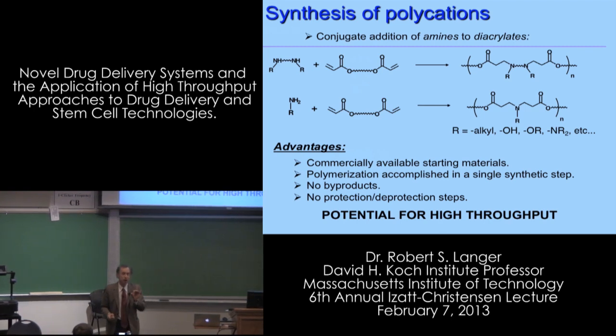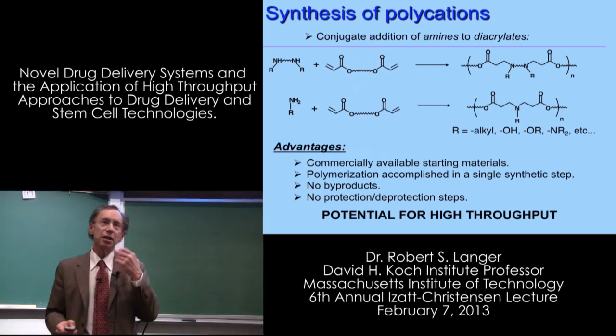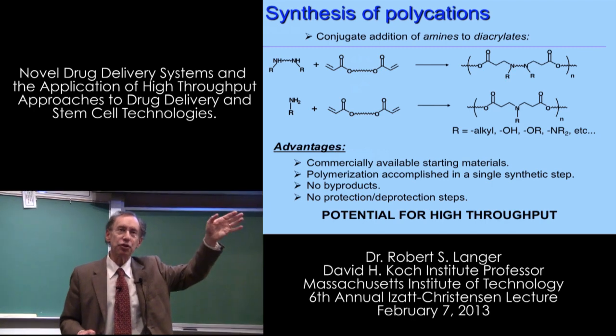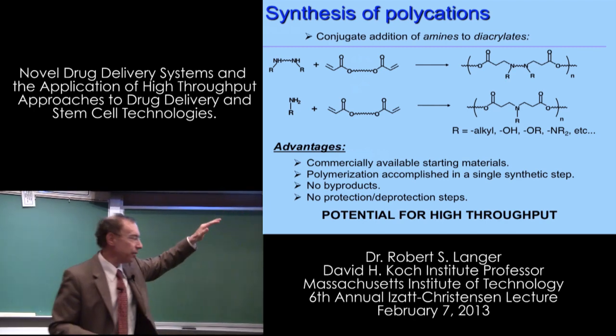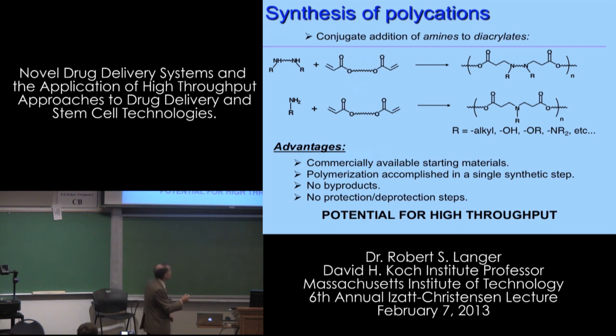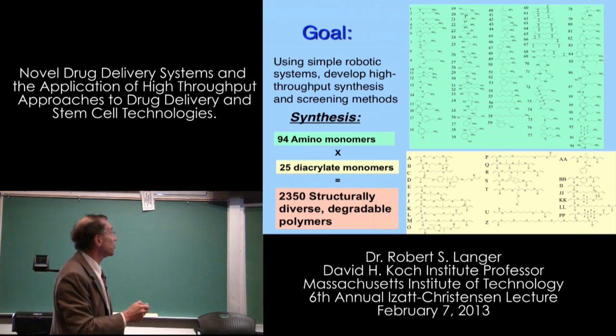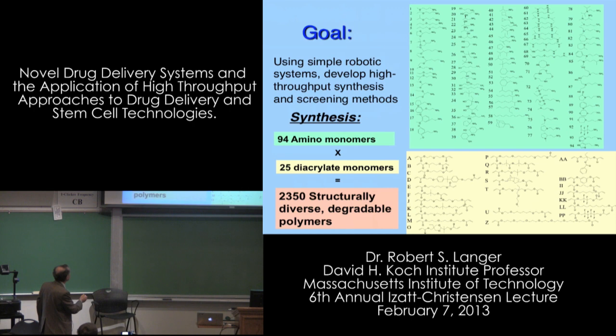Now, I put Dave in the same office with a very good molecular biologist in our lab, Dan Anderson. And so what they did is they worked out ways to not only synthesize thousands of these, as I'll show you, but screen them for gene therapy and other things pretty quickly. And so here is, nobody should take this down, but basically, what they did is pick 94 amino monomers and 25 diacrylate monomers, and they reacted each of these with each of these. The only thing I want you to notice is chemical diversity, enormous chemical diversity. So they synthesized all these, made over 2,000 polymers.